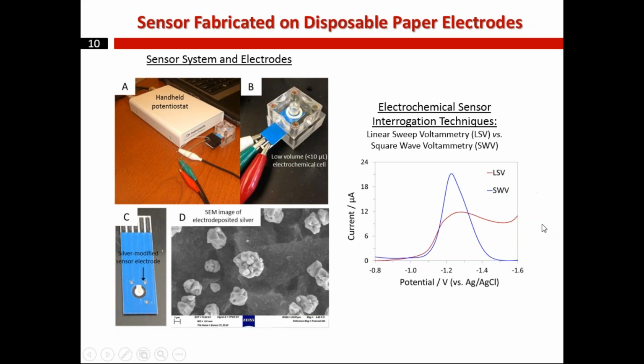optimize different parameters that affect detection of nitrate. The first thing that we optimized was the type of electrochemical technique that we can use for detection of nitrate. So in this case, we studied the sensor response with linear sweep voltammetry, or LSV, and square wave voltammetry, or SWV. And as you can see here in this picture, we observed that when we interrogate the sensor with SWV, we could get a much sharper peak for reduction of nitrate compared to LSV. Therefore, we decided to keep on using SWV.